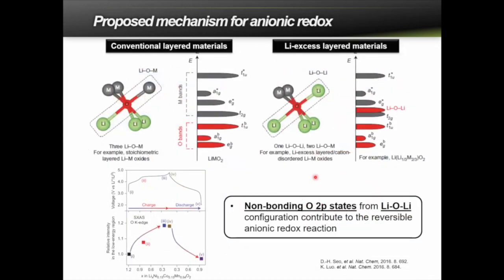There have been heated discussions on what can make these anion redox reactions possible and how they can be stabilized. I'm not going to go into the details of this discussion, but one consensus and simple explanation was that the local environment of oxygen in the layered structure, such as three transition metals above and three lithium ions below, shifts from this in the conventional layered structure to this with additional lithium in its surrounding in the lithium excess material. So this particular oxygen generates a new state in the density of states and allows additional accessible capacity.